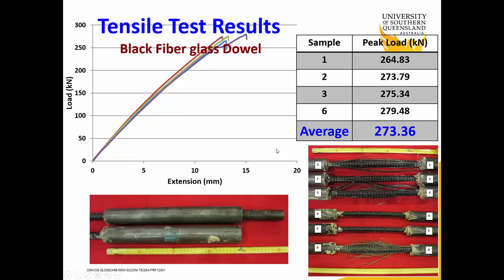A tensile test was conducted on black fiberglass as shown in this figure. The vertical axis shows load in kilonewton and the horizontal axis shows extension in millimeter. You can see the tensile strength is around 273 kilonewton as shown here, and this shows the photo of the sample after failure.